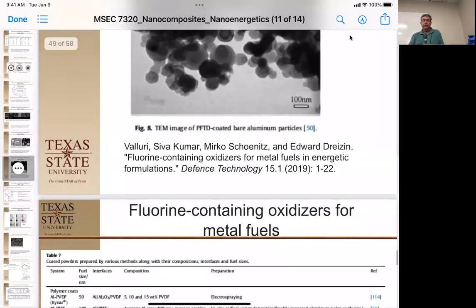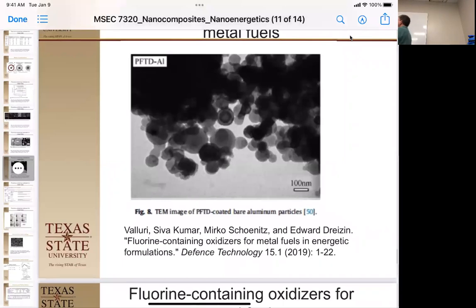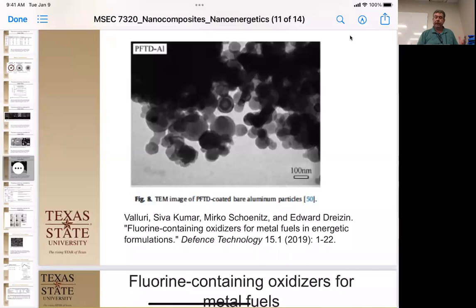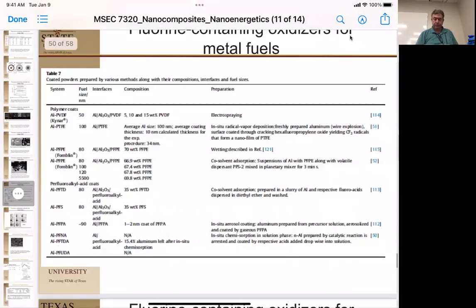So what they did was to get a better mixture than just mixing the big Teflon with the little aluminum or the big Teflon with the nano aluminum. They actually were trying to coat them directly on top. So you have this intimate involvement of everything. A lot of fluorine already spread all around the system at once.